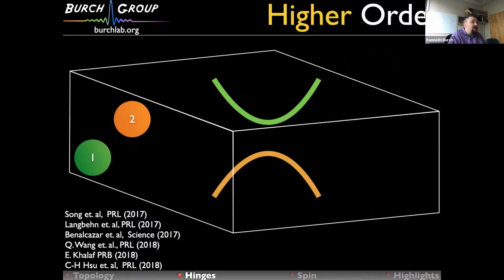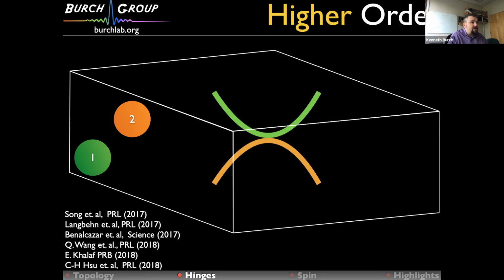Imagine I have a system with two atoms, and I want to keep inversion just to keep things simple, but it's not necessary. This could be gallium arsenide or silicon or whatever, two distinguishable atoms where, say, my conduction band comes from atom 1 and my valence band, roughly speaking, comes from the states of atom 2. Even if I was an insulator, it's clear that most of my electrons, at least the valence electrons, are sitting around atom 2. Now let me turn on some interactions, say spin orbit coupling or pressure, whatever you want. I bring these two states together and they mix and hybridize. And then I reopen my gap.